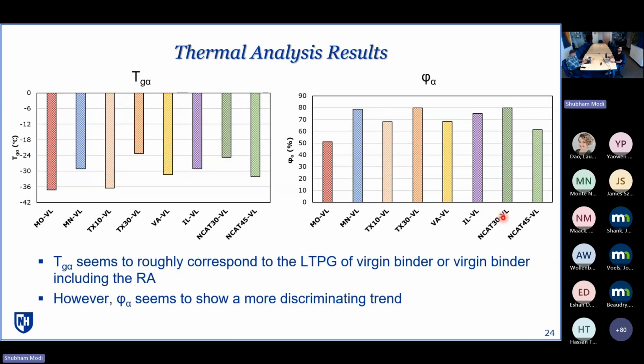With this, here we are discussing the thermal analysis from DSC testing. And we can see that Tg alpha more resembles the trend of LTPG of virgin binder, including the RAs. And on phi alpha side, it shows a more discriminating trend in a way that the Missouri mixture here had the highest RAS content, and it clearly showed the effect of a higher RAS content by showing lower values of phi alpha, meaning higher phase separation, and it differentiates between the binder sources. And if we had the same binder source but different RAP content, it was also able to capture that effect.